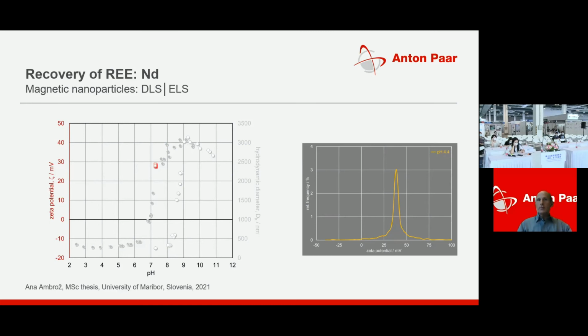The initial zeta potential of the magnetic nanoparticles reads plus 28 millivolts, representative of the protonated amine groups of the functionalized particle surface. By increasing the pH, we find a decrease in the zeta potential, which approaches 0 millivolts at the so-called isoelectric point, occurring at pH 7.8.